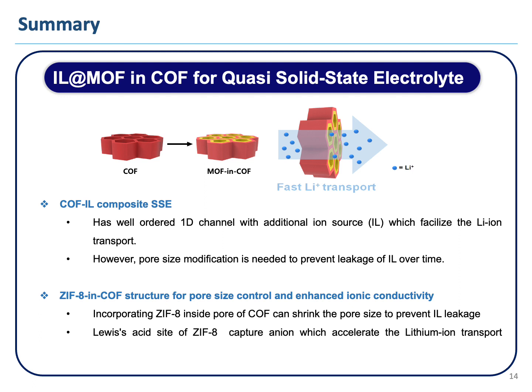For summary, we propose an ionic liquid and MOF in COF structure for quasi-solid-state electrolyte. First, the COF-IL composite solid-state electrolyte has well-ordered one-dimensional channels with additional ion source IL, which facilitates the lithium ion transport. However, pore size modification is needed to prevent leakage of IL over time. So, ZIF-8 in COF structure is introduced for pore size control and enhanced ionic conductivity for quasi-solid-state electrolyte. By incorporating ZIF-8 inside the pore of COF, it can shrink the pore size to prevent ionic liquid leakage, and also the Lewis acid site of ZIF-8 captures anions, which accelerates the lithium ion transport.